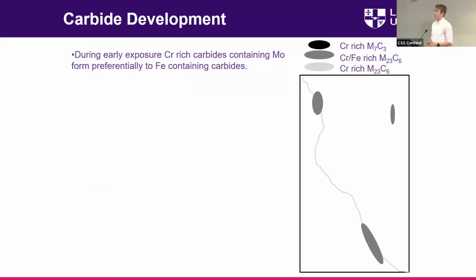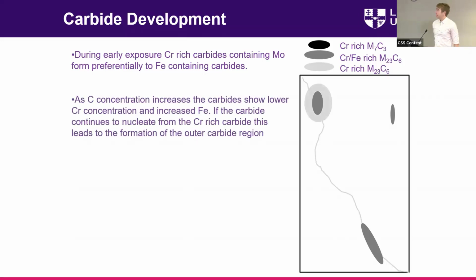performed. So from the experimental and the thermodynamic modelling, I developed a model of what we thought was happening with the exposure time, so increasing carbon. Initially, during the exposure, you see chromium-rich carbides forming with molybdenum, and these are forming preferentially because of the higher availability of the chromium within the substrate. As the carbon concentration increases, the carbides which are now forming show lower chromium and higher iron concentrations. So some of these might be nucleating off the previous carbide, so that's why you end up with the coring and the chromium-rich centres and the slightly lower chromium outside.